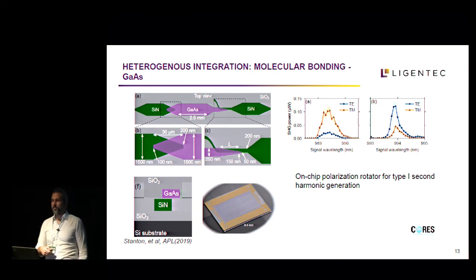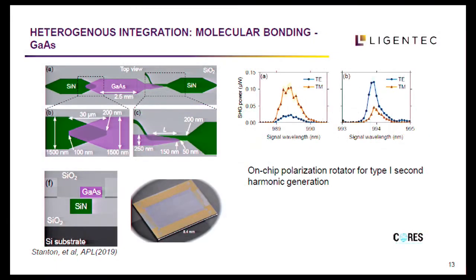Again, working on bonding, you can say, okay, lithium niobate is one wafer, but what about if we want to put gallium arsenide? And in this paper from Stanford, again under the DARPA CORES program, we do just that. So we do the silicon nitride waveguide, and then we bond on top of it a gallium arsenide device. And this gallium arsenide device does a polarization rotation, that's why it's a bit offset, and the second harmonic generation.